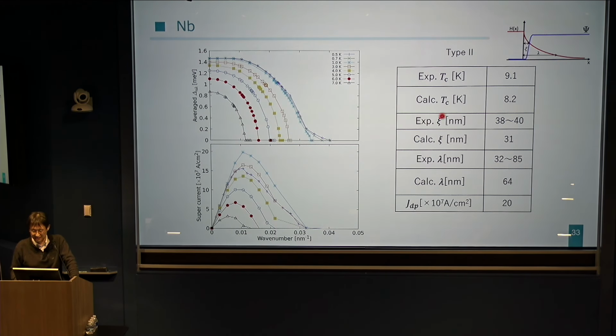Critical temperature, coherence length and magnetic penetration depth. We see that the agreement between theory and experiments is all good. The experimental measurement of lambda is actually a bit difficult, more difficult than Xi. Depending on the literature, there are some ambiguities, but I would say that the agreement between theory and experiment is good. And importantly, from this result, we can say that lambda is larger than Xi. So niobium should be a type 2 superconductor. It's consistent with the experiment, and it should be noted that, without referring to the experimental data, we can predict that niobium is a type 2 superconductor from this calculation.